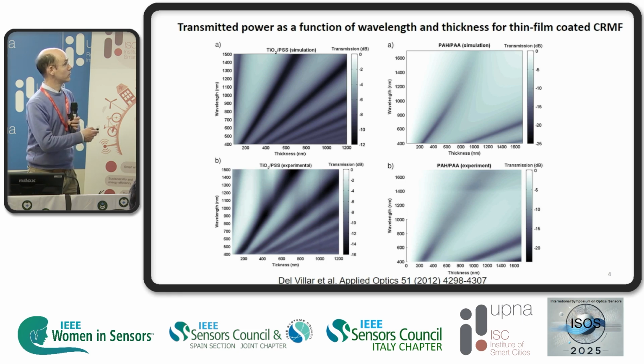If we compare a thin film of high refractive index with a thin film of lower refractive index, here the wavelength shift is lower than here. So it is better to use high refractive index materials. Here is the relation between theory and experiments, and it is important to highlight that with a simple simulation method that considers ray optics, we can obtain quite accurate results. This is because we are working with cladding removed multimode fiber, which is a thick waveguide. Probably with single mode structures, we need more advanced software.